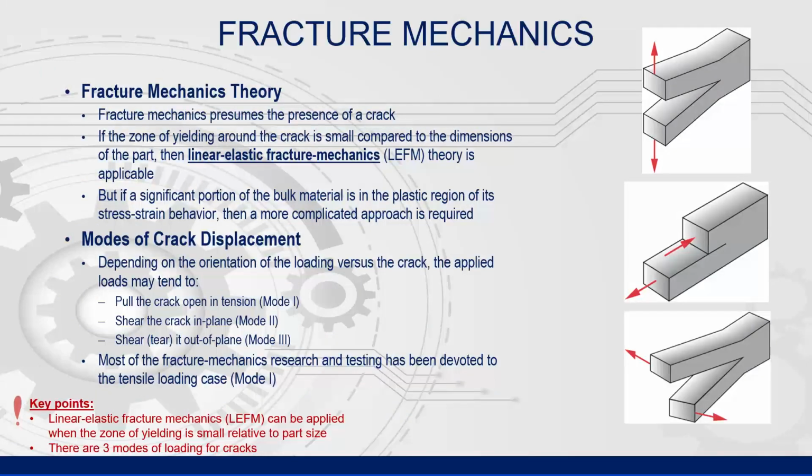Fracture mechanics assumes that there is the presence of a crack. If the zone of yielding around the crack is small compared to the dimensions of the part, then linear elastic fracture mechanics, LEFM, is an applicable theory.